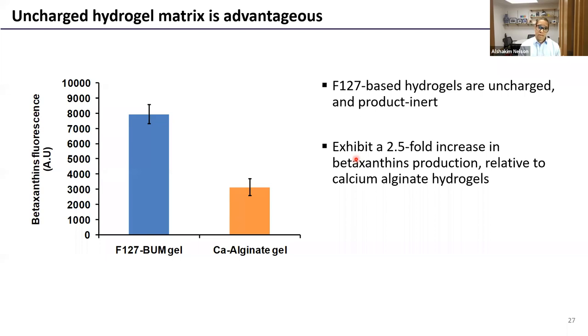So for one, our hydrogel networks are covalently cross-linked versus calcium alginate, which is ionically cross-linked. And the calcium alginate gels can start to disintegrate over time versus our gels, which are more robust. But also, if you're producing a product or a molecule that has any type of charge associated with it, that charge can interact with the calcium alginate gel.